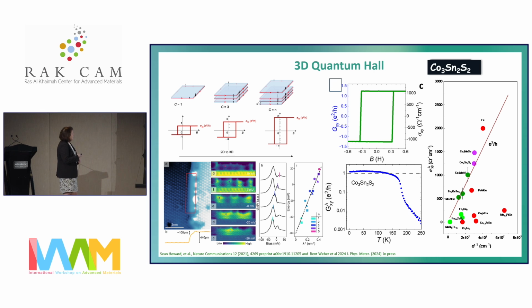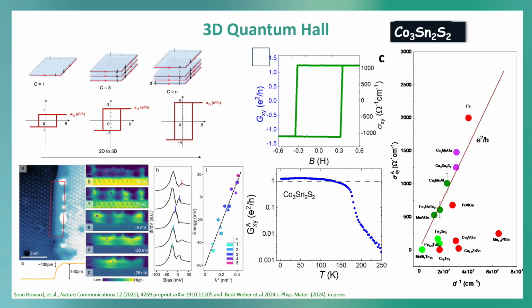Anyway, the other thing is you see also in this material a very interesting quantum effect. If you simply do STM here at the edges of the cobalt 3 tin 2 sulfide 2, you apply a voltage bias, and you see nice edge states which are quantized. And if we look into detail in this material and measure the conductivity per magnetic layer, you see something like, if you see this curve here, it's quasi-quantized per layer. So this is an idea that we think in this magnetic material, sometimes if they show exactly the property, you see probably a 3D quantum Hall effect, which is quantized per layer in this material.